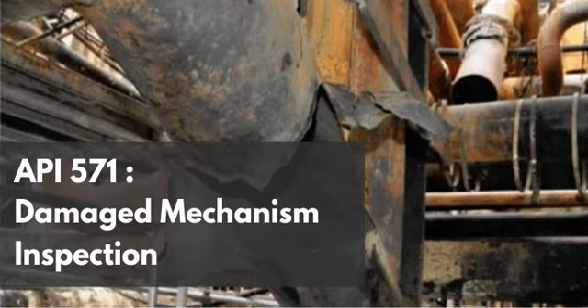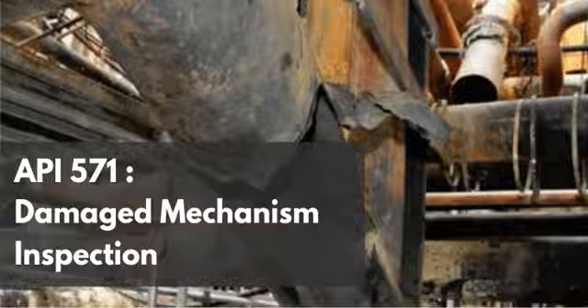And what's the first one? First, the cracking is predominantly intergranular. Second, the crack network is oxide-filled. Okay, intergranular and oxide-filled. And the third? Third, the cracking morphology exhibits branching. If you don't have that specific triad of characteristics, you cannot definitively classify the failure as Amine SCC.